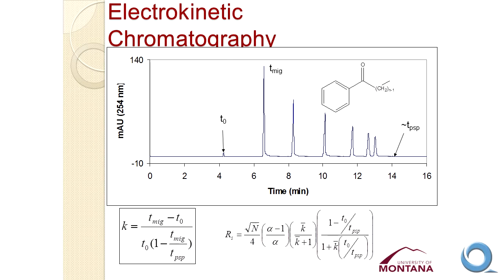All right, if we do this technique properly and get a nice result like this, what we see is T0, which marks the migration time of an analyte or a compound that does not interact with the pseudostationary phase. So that compound, in this case, is acetone, has zero affinity for SDS micelles, and so it migrates with the electroosmotic flow and gives us an indication how long it takes the electroosmotic flow to come through the system. These compounds are being separated.